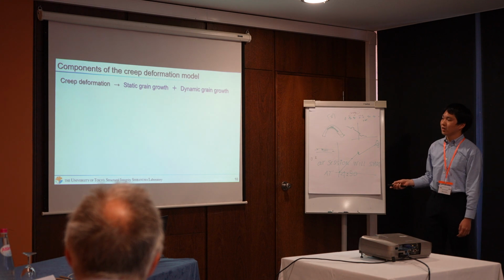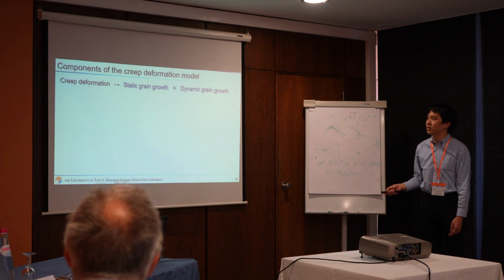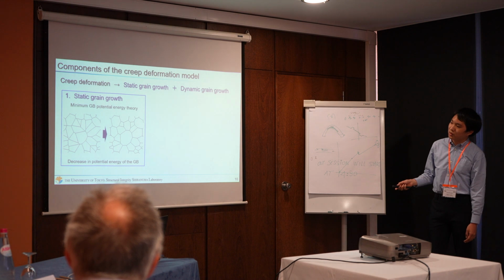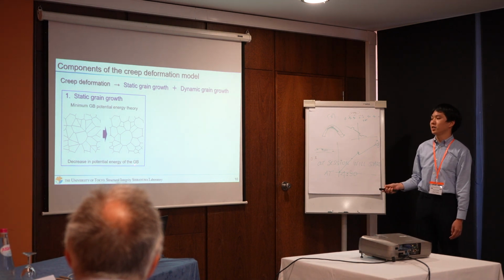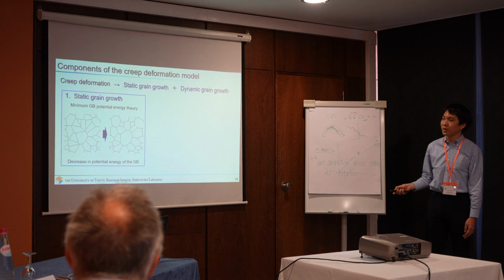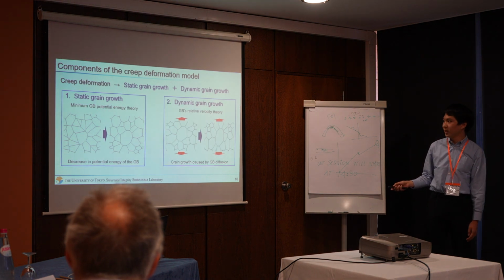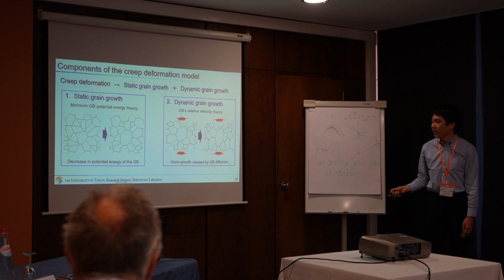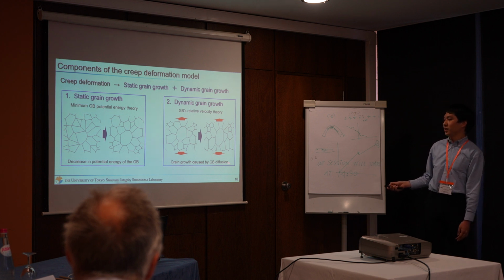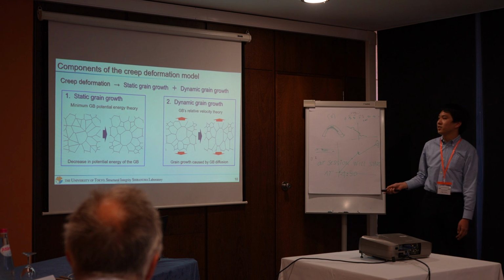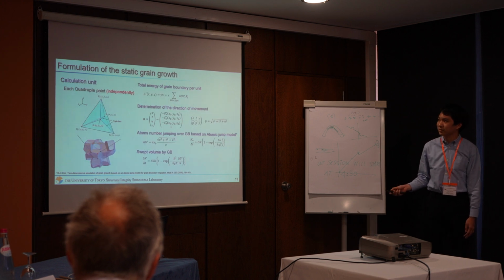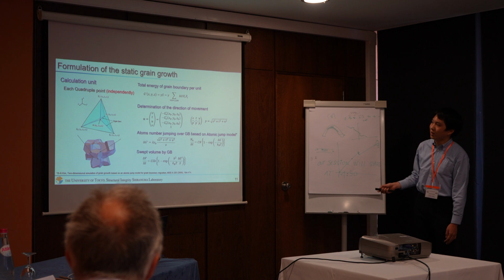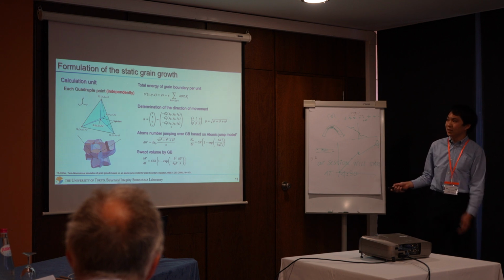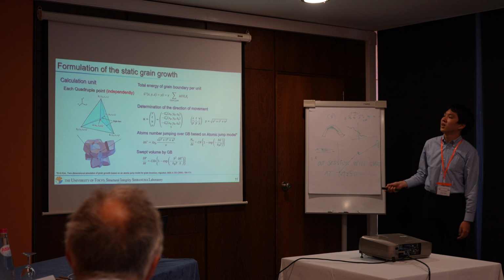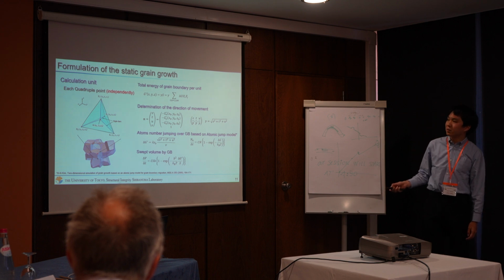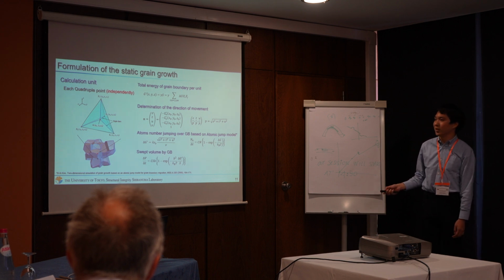Creep deformation consists of static grain growth and dynamic grain growth. Static grain growth is a decrease in potential energy of the grain boundary based on minimum grain boundary potential energy theory. Dynamic grain growth is the grain growth caused by grain boundary diffusion based on the grain boundary relative velocity theory. And this is a formulation of the static grain growth. The formulation is complex, so I'll explain some important points of the formulation.